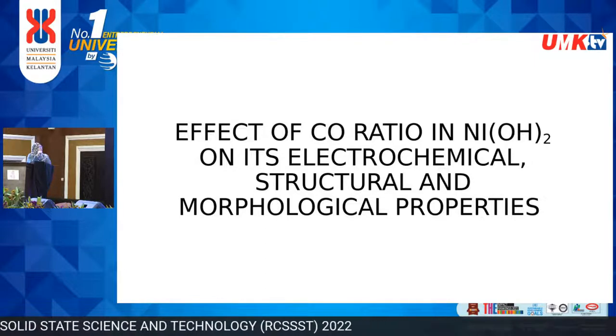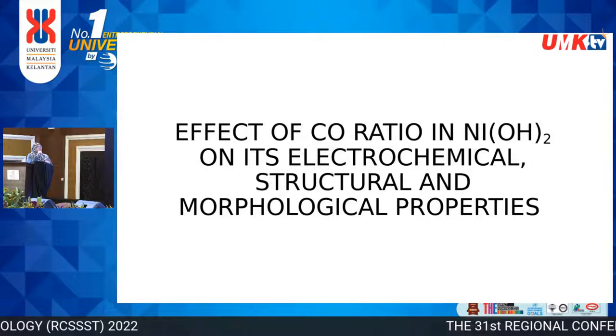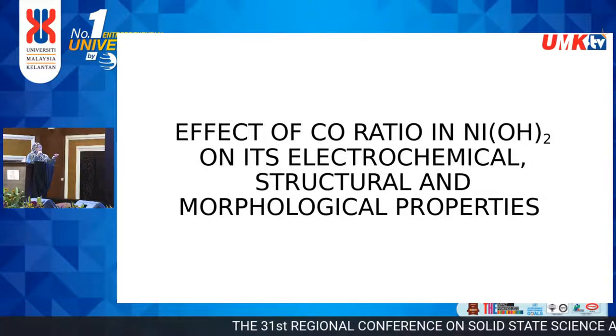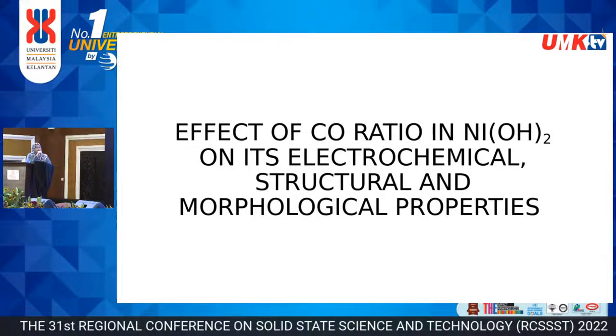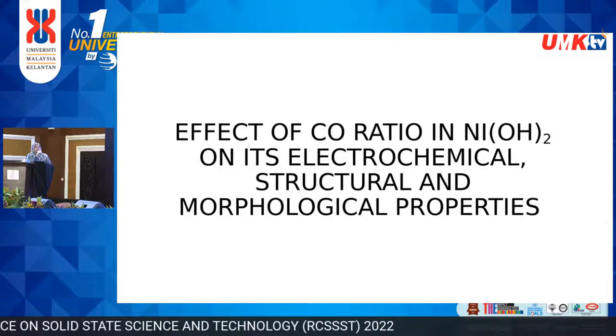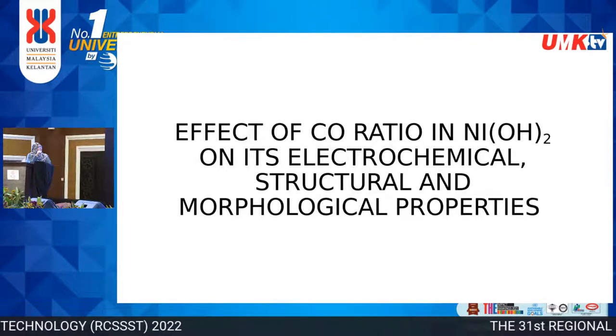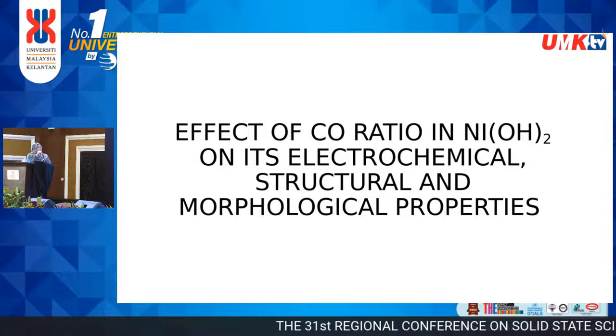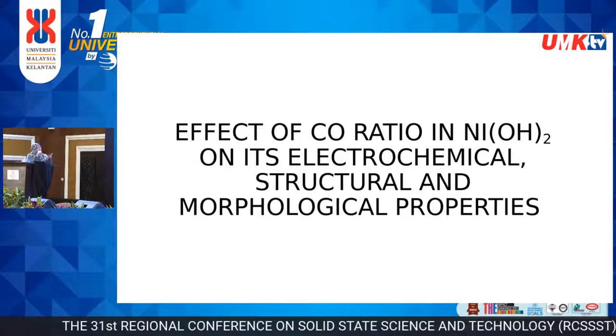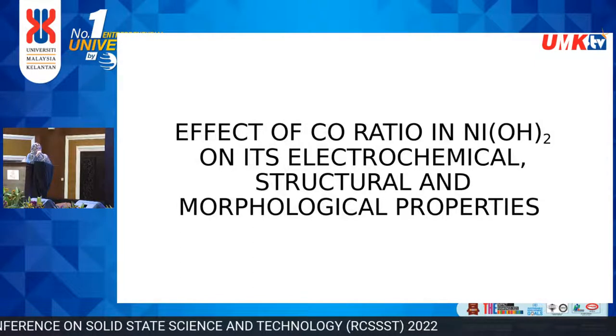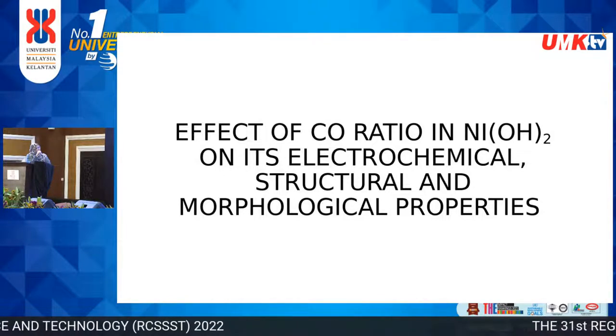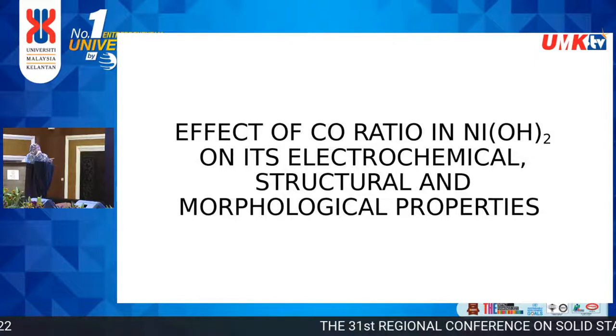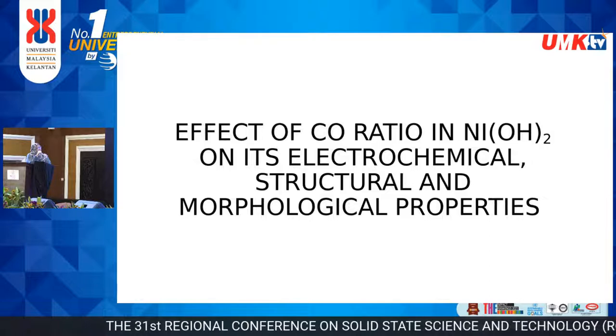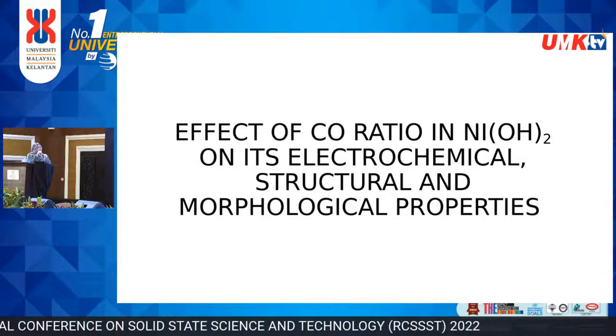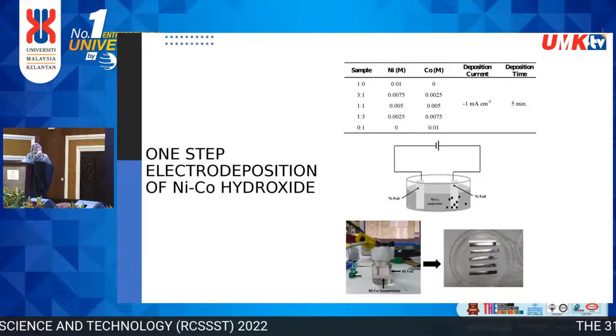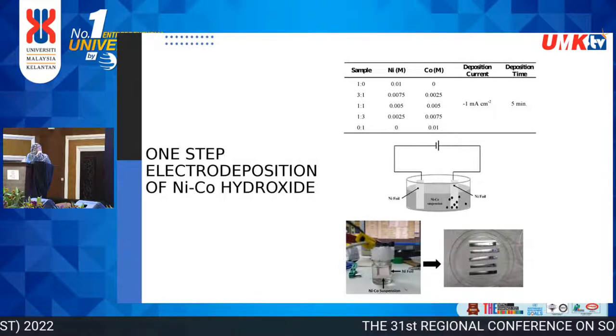We also do the experimental part after the DFT calculation to prove that the DFT method is reliable. So we do the one-step electrodeposition of nickel cobalt hydroxide with the ratio obtained from the DFT calculation. If you can see, the deposited samples are very thin because we only deposit for 5 minutes at negative 1 milliampere per cm square.